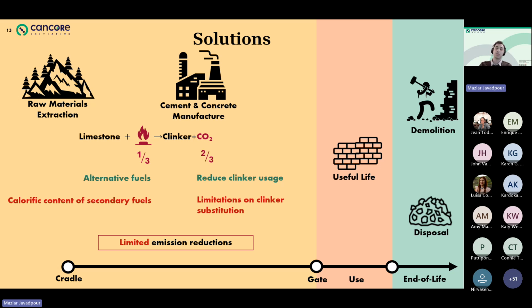And the second solution that we have for this problem is reducing the clinker, which is the main constituent of cement, right? And reducing the clinker, we can use something called a supplementary cementitious material, which is going to act as if it's cement. So it's very similar in terms of how it can react and it can bind particles together. But at the same time, it doesn't have the calcination of limestone in its production process. So it's less carbon intensive. But then we really can't take out all of the clinker either. So we might be able to take out a fraction of the clinker. Depending on what the replacement is, we can take out different amounts, but we can never fully take out the clinker from the process itself, which means that we have limitations on our emission reductions.